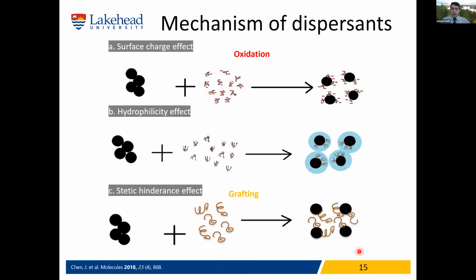When you do oxidation, the first one is the charge repulsion. So what we do is that we add lignin-based dispersant in the system to introduce some charges to repel particles. The other one is that due to hydrophobicity of the lignin, they can agglomerate. But if you improve the hydrophilicity of lignin, that will help the dispersion.